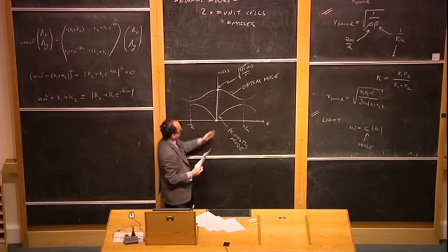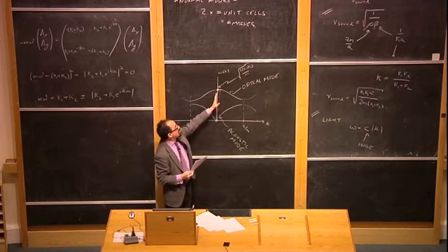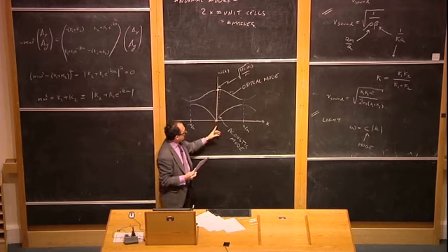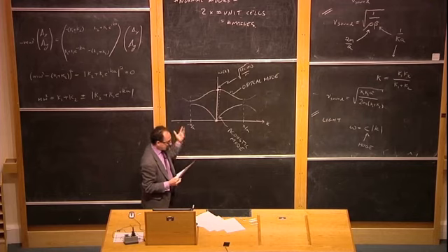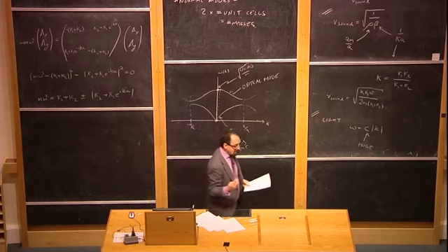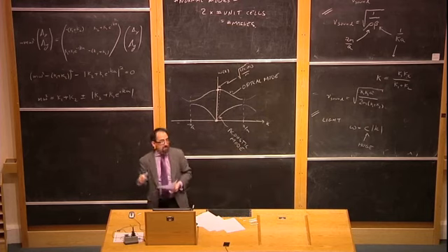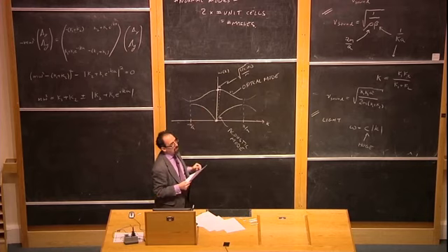The only place that can happen is right here. And the reason you're never going to match the acoustic mode is because the velocity mismatches so badly. But with the optical mode, since it has finite frequency even at k equals 0, there is a point where the optical mode frequency matches the light frequency and the optical mode momentum matches the light momentum, or even crystal momentum in this case. So that's the nomenclature of why people call this the optical mode. Whenever you have interactions with light and vibrations, it's inevitably the optical mode.